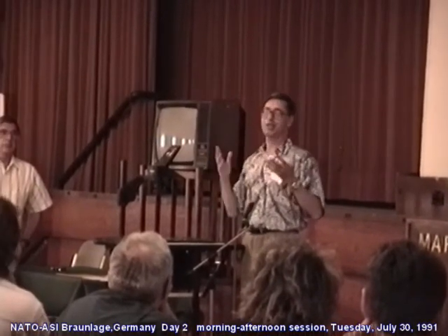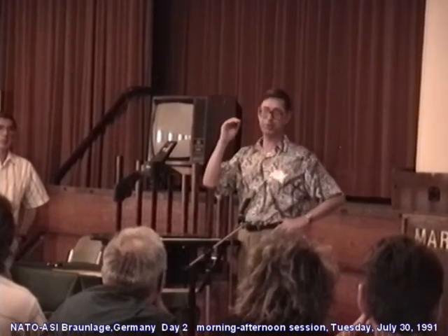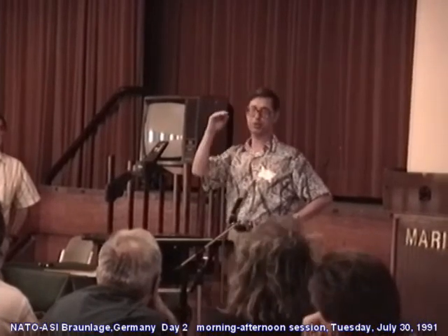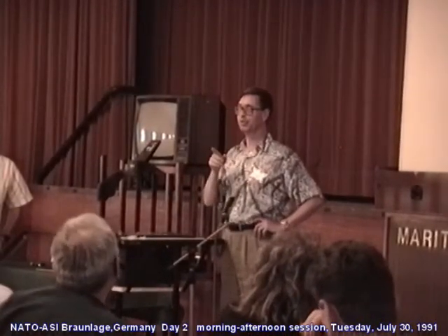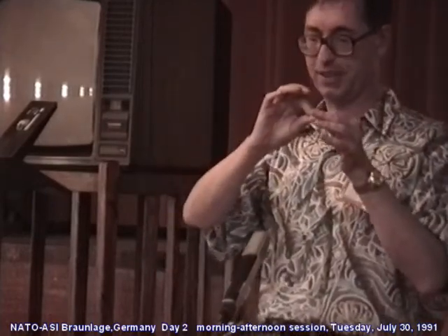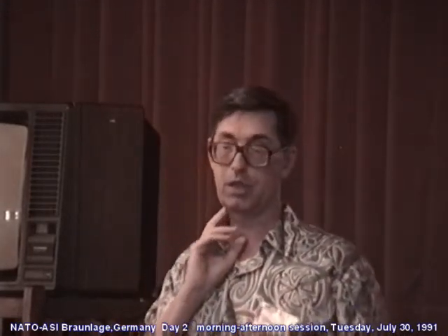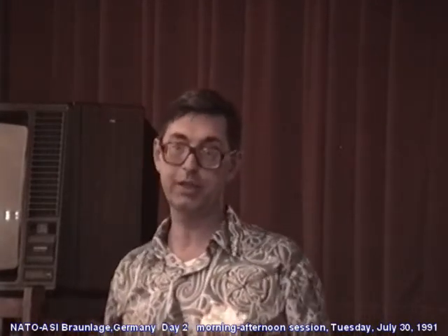Stick slip is usually explained by a difference between static friction and dynamic friction, with a static friction higher than the dynamic friction. And I suppose if you look at the friction versus velocity, you have to study in logarithmic diagrams to see if the coefficient, like for peeling, is a curve increasing and decreasing. But it is difficult to measure the friction coefficient in the decreasing branch, because we immediately have a stick slip. It is unstable. And as friction is a dissipation of energy in the subsurface, we know only that the dissipation decreases when the strain rate increases.